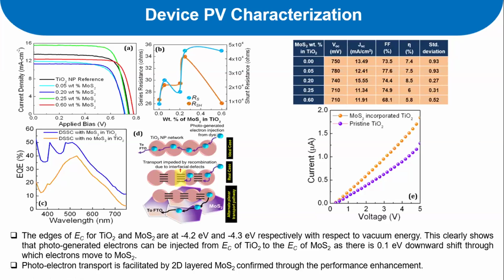So that shows that there is an optimum value at which the photovoltaic device can work better compared to the reference device, which doesn't have any 2D layer semiconductor. But if you increase further, it doesn't work that way, because there is an optimum value at which the photo conversion efficiency can be increased. That shows that the incorporated 2D layer semiconductor in the electron acceptor actively absorbs the photons from the solar spectrum very efficiently compared to the organic dye molecules.